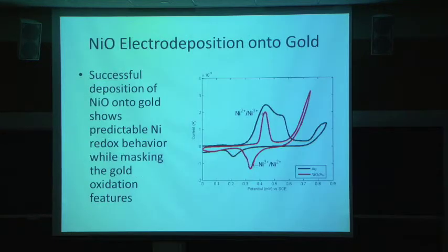Okay, so this is what it kind of looks like. We use a nickel nitrate bath. We can electrodeposit the nickel onto the gold disc. When we do that, the black line here is our gold disc. When we put nickel oxide on top, we get the red line. It completely masks the gold. We see no evidence of the gold. We see very crisp, clear nickel 2+, 3+ peaks. And we can make this film extremely thin. We don't know exactly how thin, but it's pretty thin.